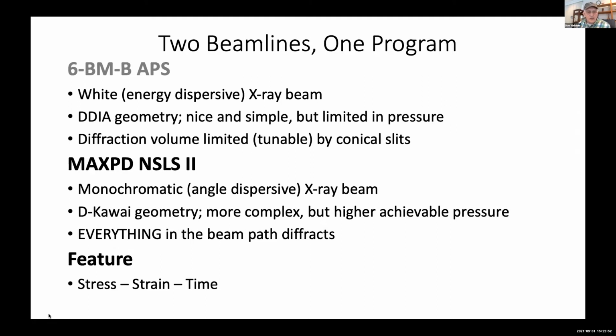They share some things in common, and there are some differences between them. The APS system is a white beam, and we do energy dispersive analysis. The NSLS2 is a monochromatic beam, so we do angle dispersive diffraction. In both systems, we have a large volume high pressure system that is complete with a uniaxial capability. So these both can produce high pressure and high temperature. One can superimpose on the system a differential stress. But there is a different design.